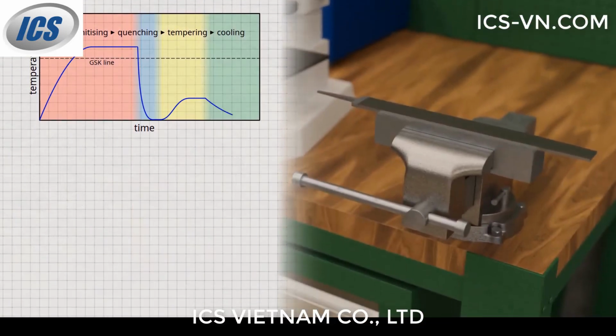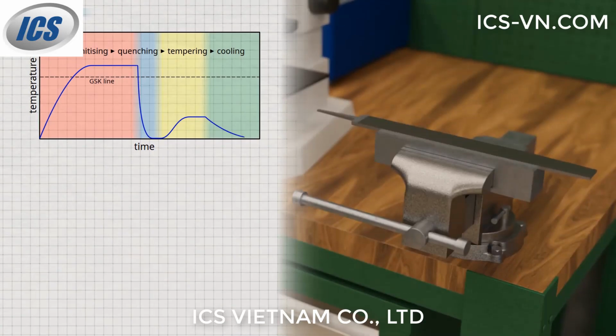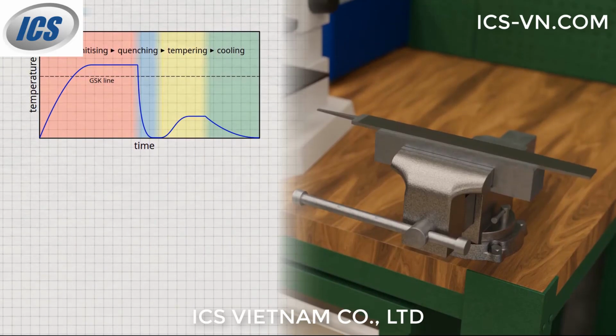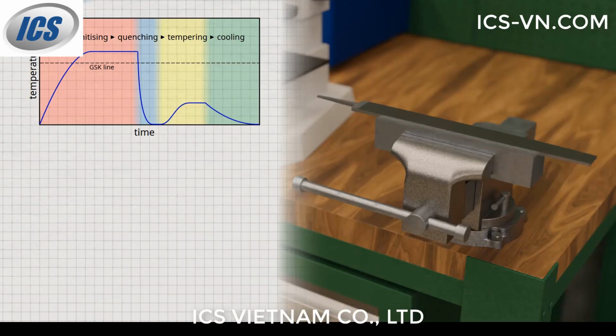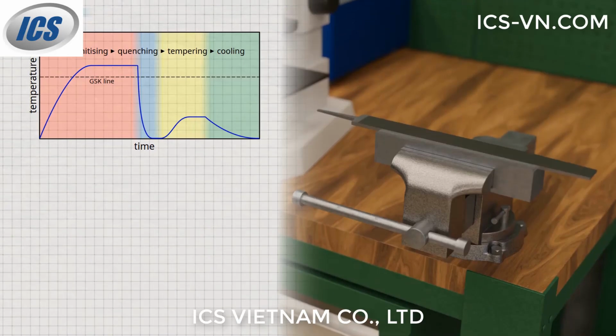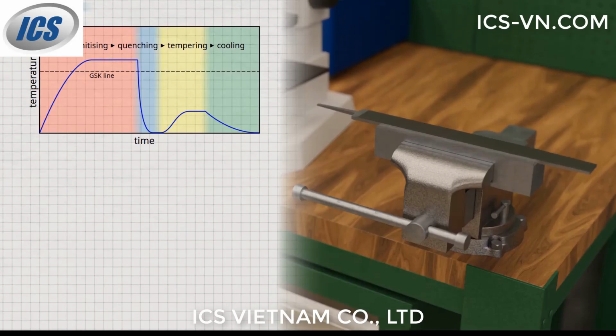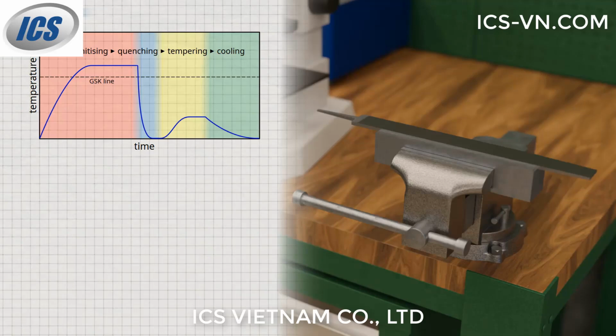Note that the martensite microstructure after quenching is ultimately a state of disequilibrium, as the microstructure could not reach thermodynamic equilibrium due to the rapid cooling. However, the subsequent heating during tempering gives the microstructure time to develop towards thermodynamic equilibrium again. This results in the diffusion of carbon from the martensite lattice. Although hardness and strength may have decreased after tempering, they are still well above the original microstructure before quenching.